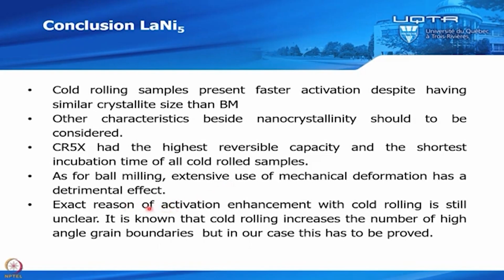Up to now, the exact reason for activation and enhancement with cold rolling is still unclear to us, but it's known that cold rolling increases the number of high-angle grain boundaries. But in our case, it still has to be proved. We still have to do some experiments about that.